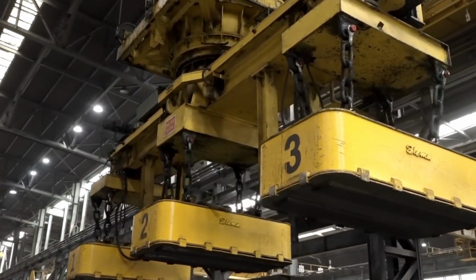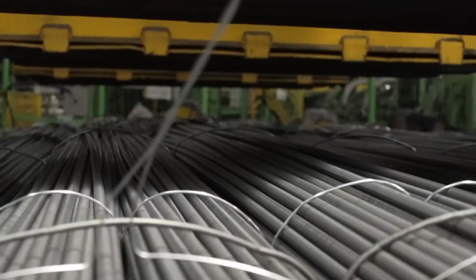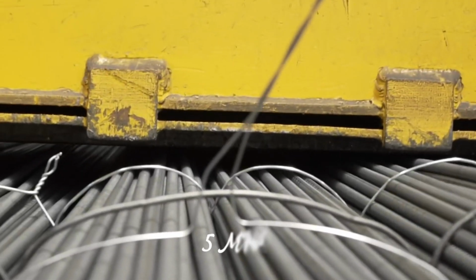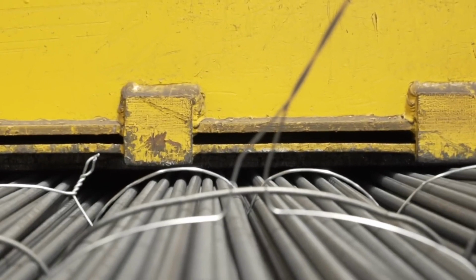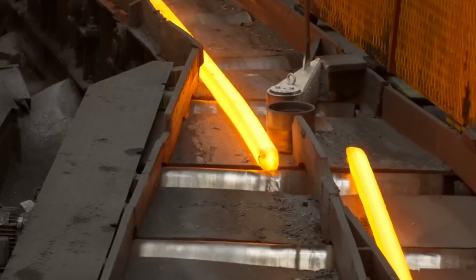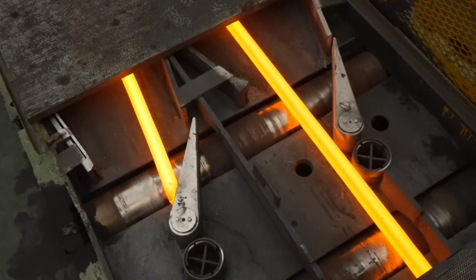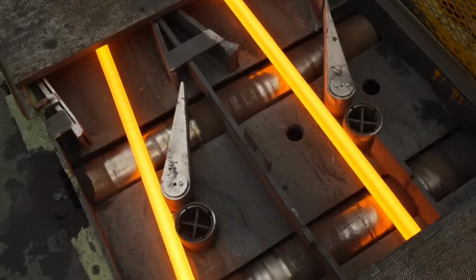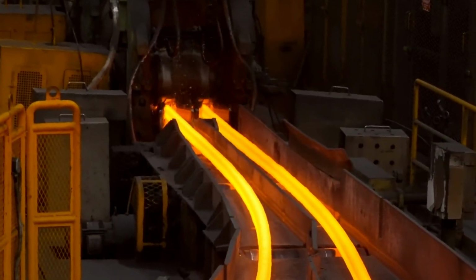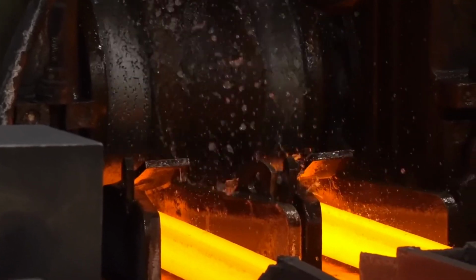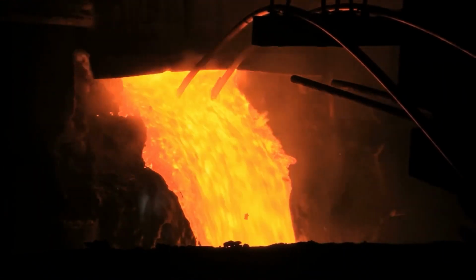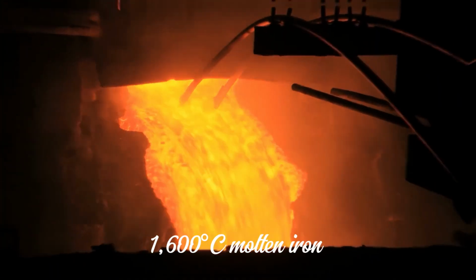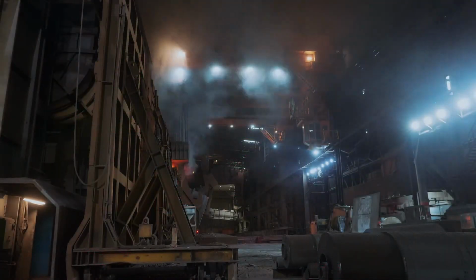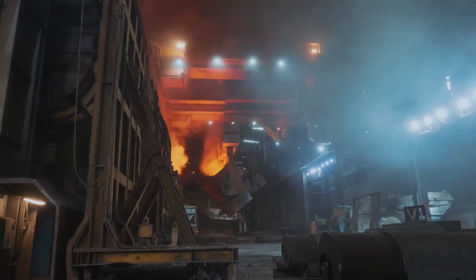Straightening rollers correct residual curvature. Ultrasonic sensors at 5 MHz scan for internal cracks. Cooling locks geometry and internal integrity. Inspection confirms the entire thermal and mechanical history, from 1,600 degrees Celsius molten iron to precision flat steel plates,